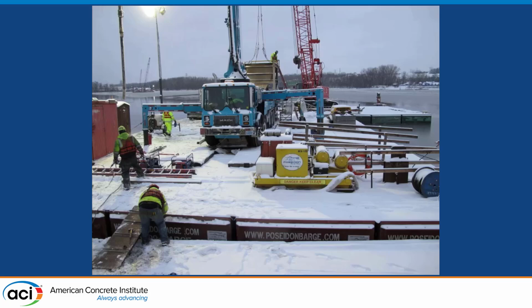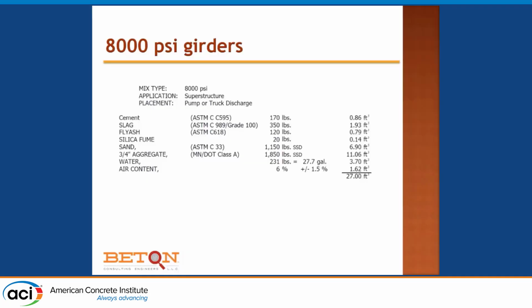It's something we've done before with MnDOT, so we weren't particularly frightened. And this is our mixture proportion for the superstructure. This happens to be for the 8 KSI transfer girders, which we'll talk about a little bit more. And you can see we're using a relatively mild, what is that, 350,